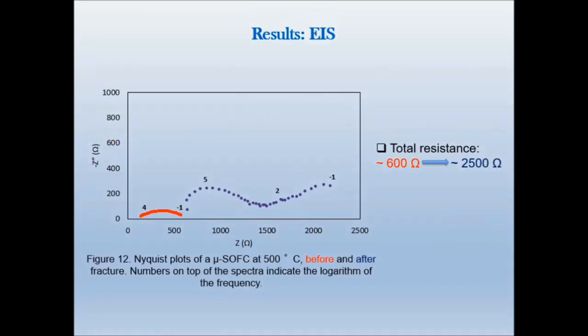About the impedance of the sample, the impedance spectra in a Nyquist plot format are shown in this figure. Spectrum in red corresponds to the sample in optimum conditions, and spectrum in blue to the sample after fracture. Even though the shape of the spectra is different compared to one another, the total impedance of the sample increased from about 600 ohms to 2500 ohms due to the fracture.